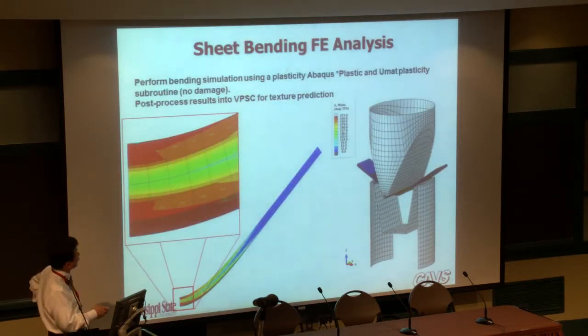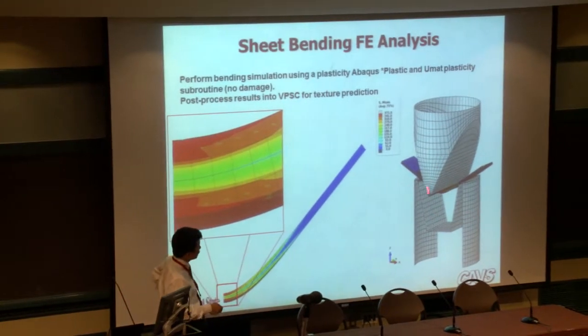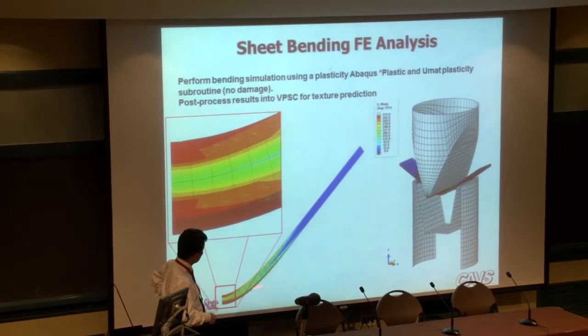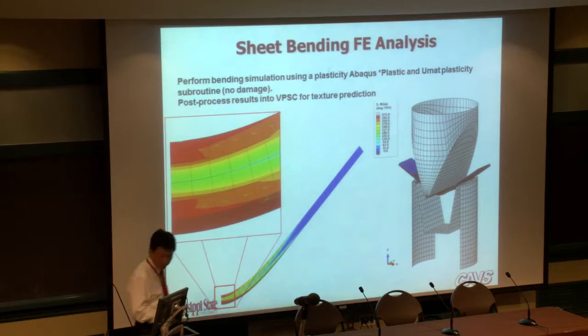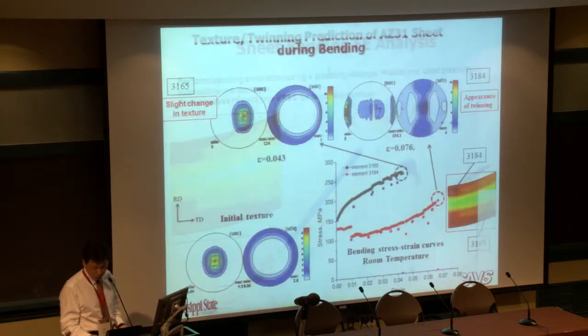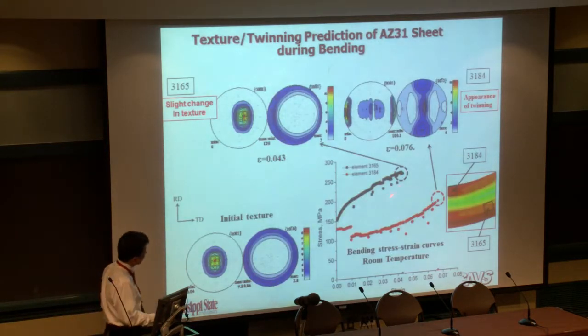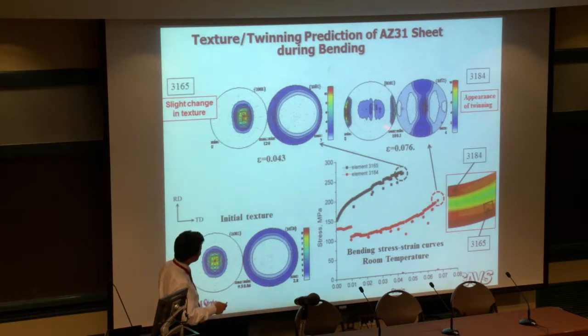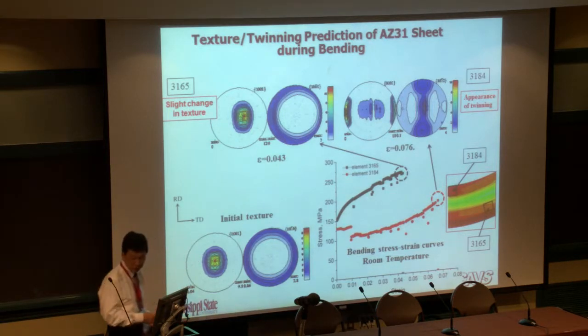Again, this is the same thing. In the laboratory, we're doing the very simple sheet forming bending, and we're tracing this local area, similar to extrusion, and then we look at the, even this tension here, we can show some sort of twinning up here. So we trace the streamline of the deformation path and see our model can describe such things.